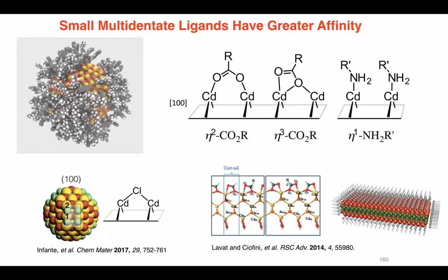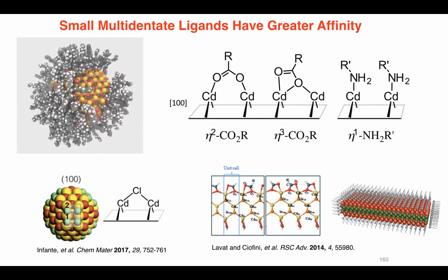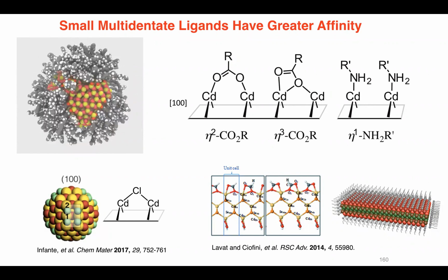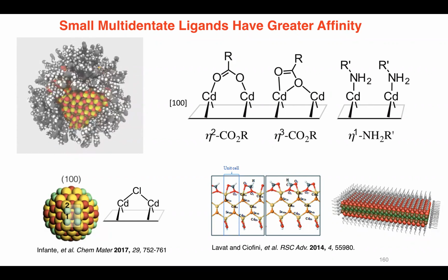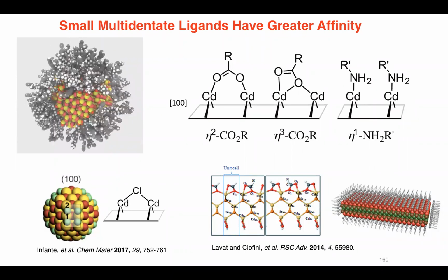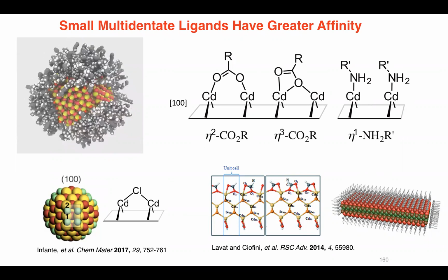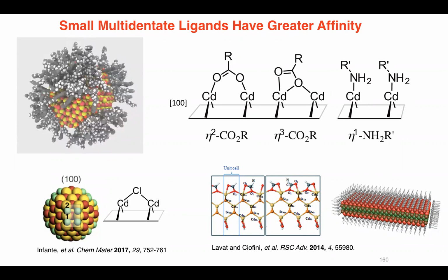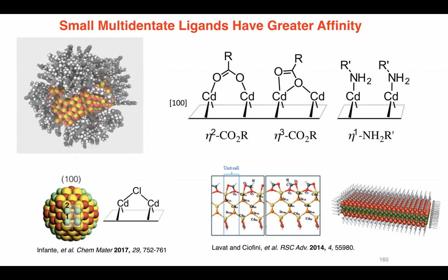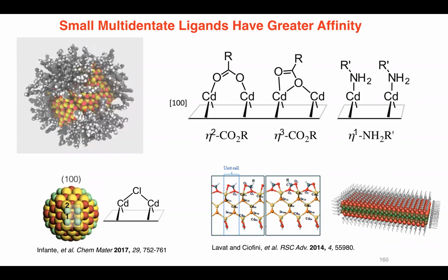We know that aliphatic chains do not pack completely because they're too big for a wide area facet of 1,0,0. So at most, we're going to put down 1, sometimes none. Now you're talking about a surface that has 2 coordinate cadmium ions, when in fact cadmium would like to be 6, right? That is a very energetic situation.